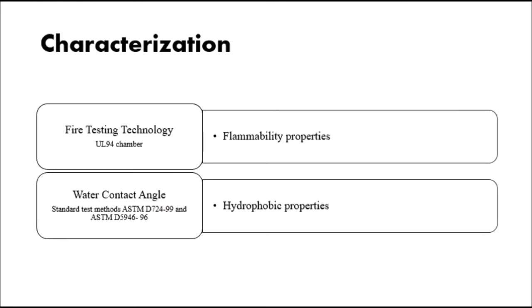The flammability properties were evaluated based on the average rate of burning using the fire testing technology. Furthermore, the hydrophobic properties were evaluated using a water contact angle measurement. So, the dispersion of TiO2 and AP in coating dispersion was confirmed using TEM images, and the morphology of the untreated and treated textile surface was investigated using SEM.